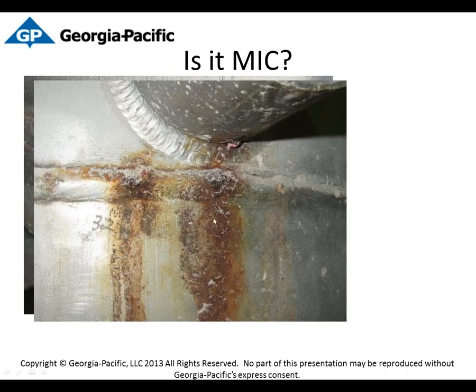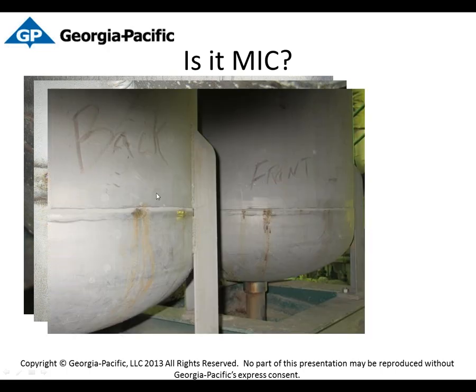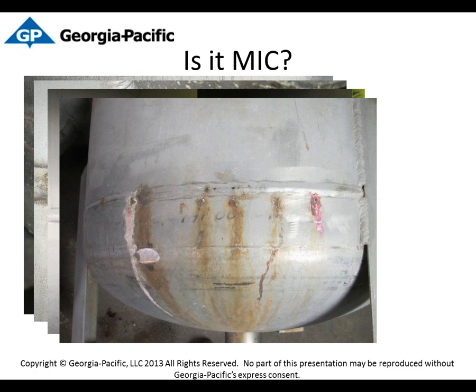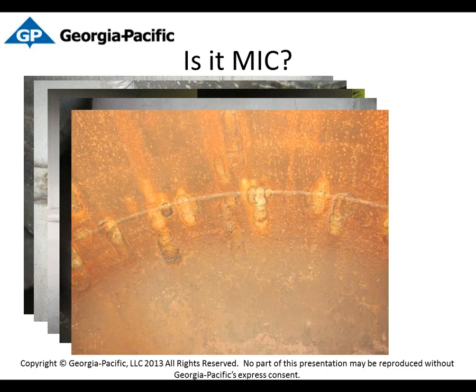Again, these are the same symptoms we see on our piping systems. We see the same things on our tanks. It doesn't really matter what the mill is or what the process is. It's always the same symptom: something on the weld line of a tank or a piping system starts to show signs of very, very small leaks. And then once we get on the inside of the piping system, you can see where tubercles have grown all along the weld line.